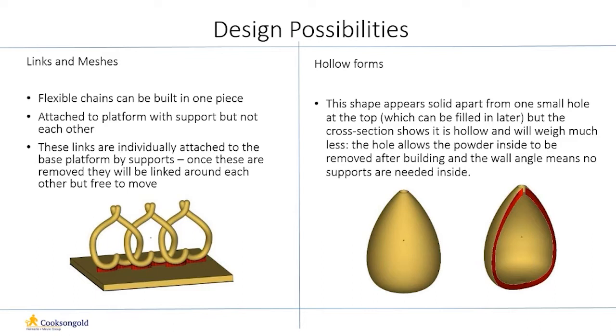The shape appears to be solid, apart from the small hole at the top, which can be filled later with a plug built alongside the part. Looking at the cross-section on the right, it shows that it's hollow and it will weigh a lot less. The hole allows the powder inside to be removed after building, and the wall angle means no supports are needed inside.